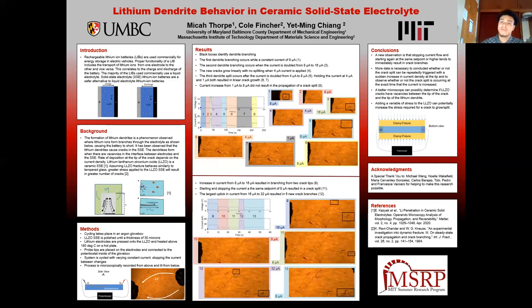Most commonly used in the field of batteries are liquid electrolytes. These liquid electrolytes have organic compounds that are flammable, and those organic compounds break down and form acids when a battery fails, and when the battery is heated up due to dendrite formation. This project provides a quantitative process to predict the growth speed and behavior of lithium dendrites in LLZO based on voltage, current, and the behavior of the crack seen visually. Establishing an understanding of lithium dendrite growth in LLZO provides a baseline for testing filament growth and other solid electrolyte materials, as well as other electrode materials.